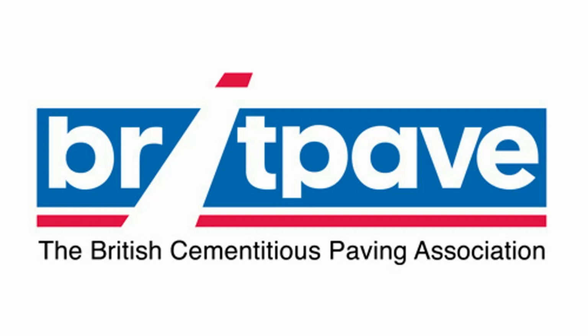No, but what we did was those samples that you saw in the laboratory, we cast those alongside the slabs on site, so they were live, only a metre wide rather than 4.5 metres wide, but their overall thickness and reinforcement was exactly the same as the site trial, and put them on the back of a flatbed and all the way down to BRE to do the testing in their laboratory. And the difficulty we had was actually the setup. The transducers weren't large enough to allow the deflection to go to complete failure of the bars. But in both the steel and the basalt case, it was the concrete that failed first.